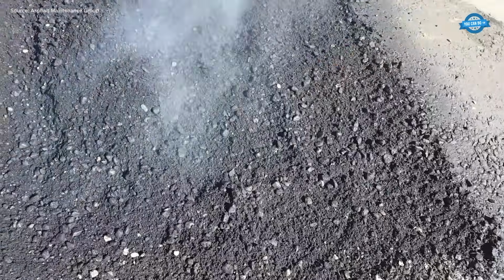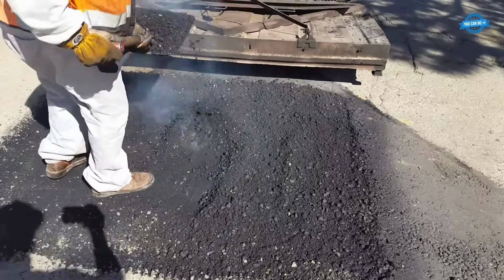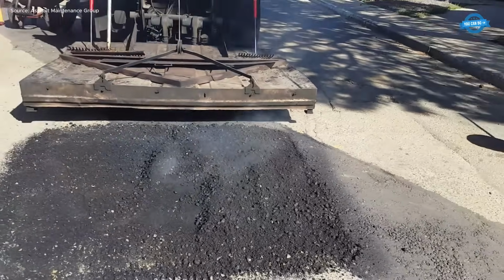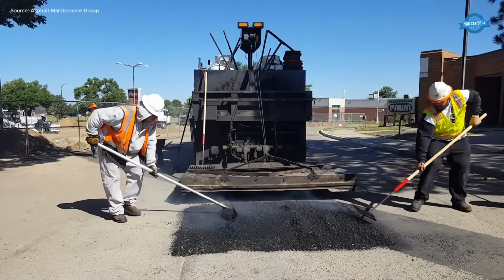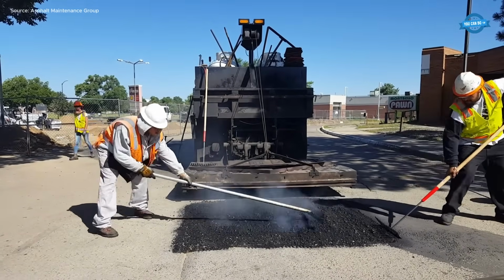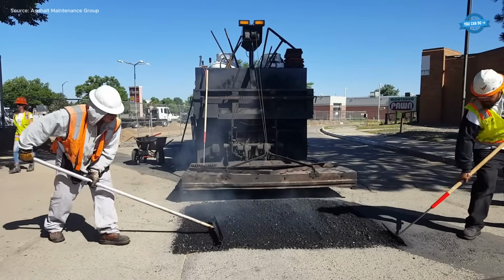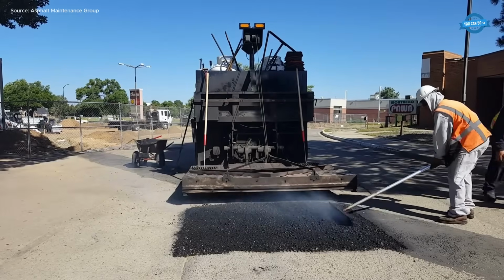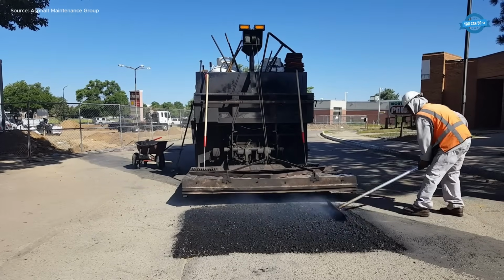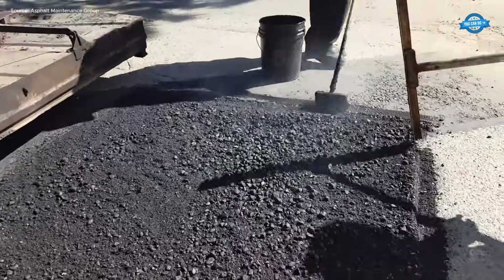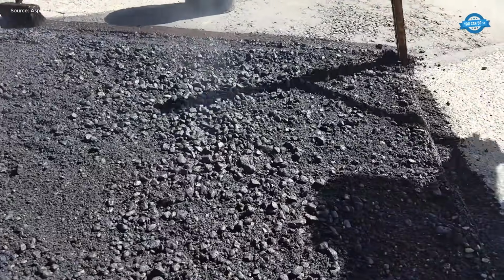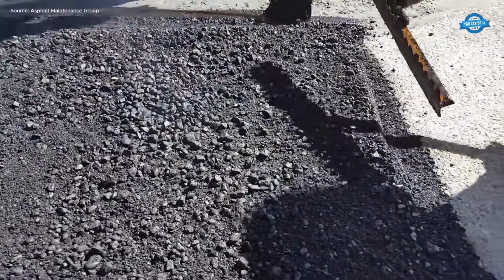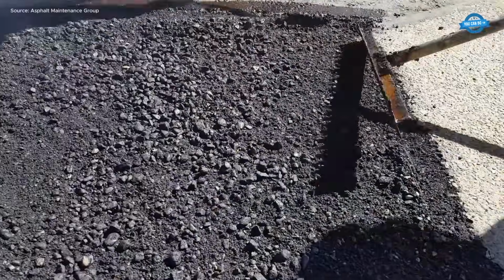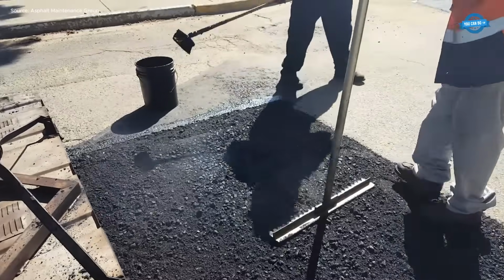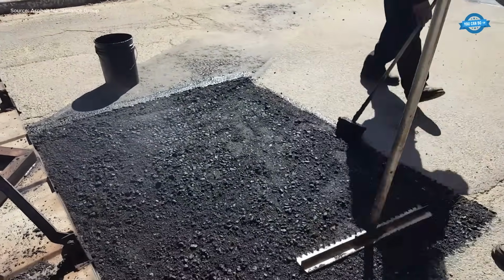Apply the asphalt using a spray system, maintaining a consistent application rate of approximately 0.05 to 0.15 gallons per square yard, depending on the porosity of the surface and the size of the repair. Ensure the liquid asphalt forms a thin, uniform layer to increase adhesion between the existing pavement and the new asphalt mix. Allow the asphalt to cure until it becomes tacky, typically 15 to 30 minutes, depending on weather conditions and product specifications.